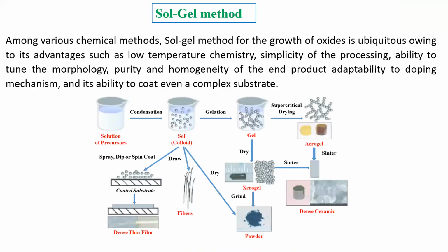Now, in the previous lecture, the professor has already explained the sol gel method. The sol gel method is very famous in wet chemistry among researchers, because one main thing is that it is a low temperature process, with no requirement of high temperature. Another thing is the purity of material. It generates very pure material. And importantly, we can even make powders. We can make fiber also by electrospinning, and we can coat this material on any complex substrate. We can make thin film, and coat around a substrate just by dip coating process.